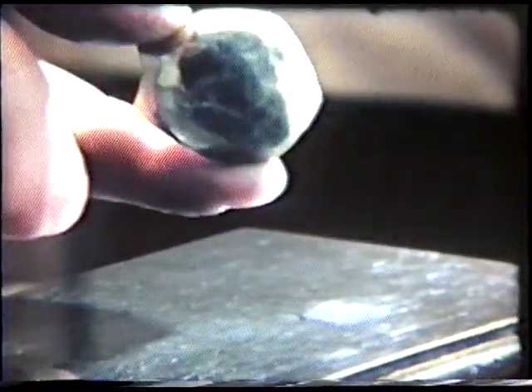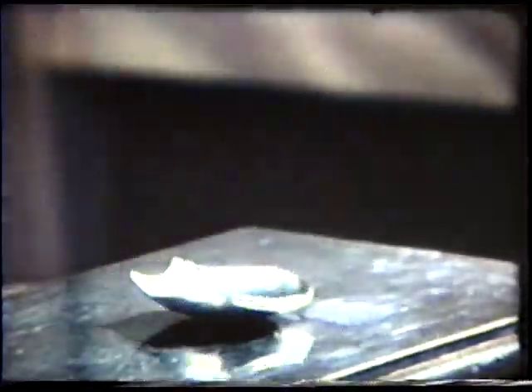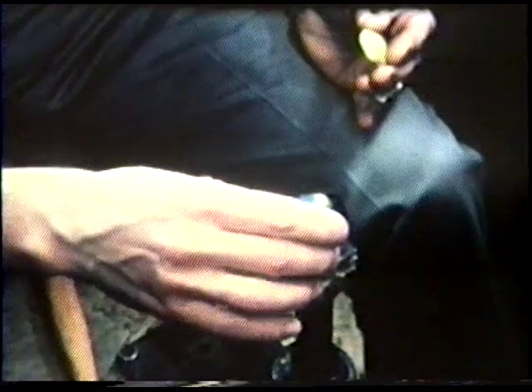Hammering hardens the gold and eventually would cause it to crack unless it is returned to a softer, more workable condition by annealing. In this process, the gold is heated to a cherry red color in subdued light and then quenched in water. This allows the structure of the gold to recover from the strain set up by the hammering. These two processes of hammering and annealing are continued until the form has reached the desired depth.